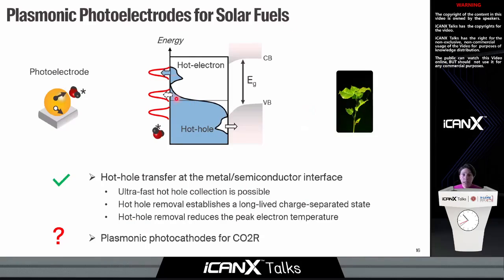So indeed, by these solid-state studies at the interface between metal and semiconductor, we could learn that ultrafast hot hole collection is possible, that this hot hole removal can create a long-lived charge-separated state, which is very beneficial for chemistry, but at the same time, we have a trade-off because this reduces the peak electron temperature distribution if we have a thermalized case. So now let's see what happens when we take this heterostructure and we use it in real applications for CO2 reduction.